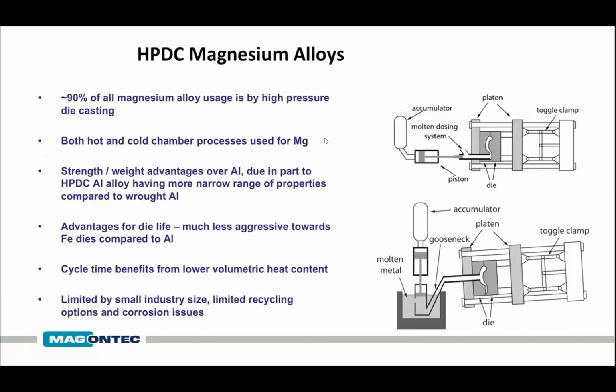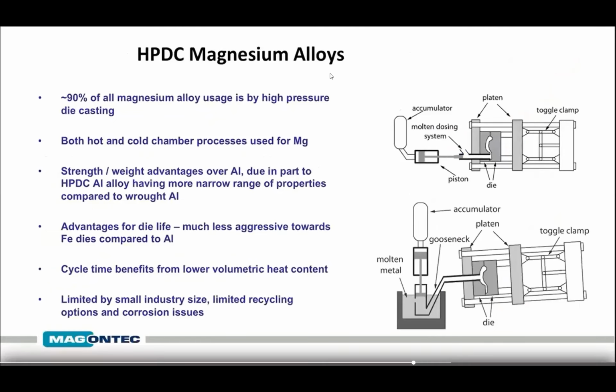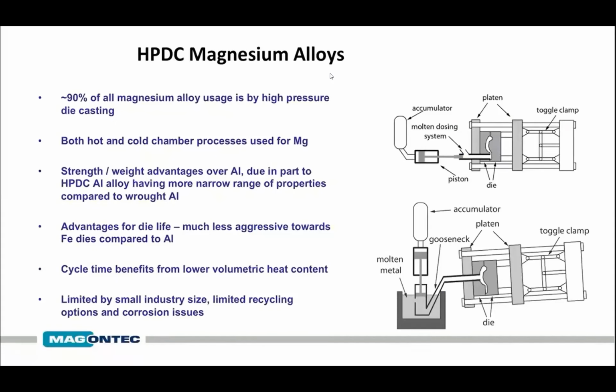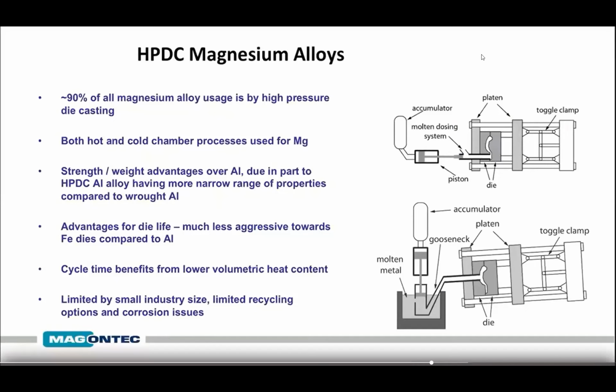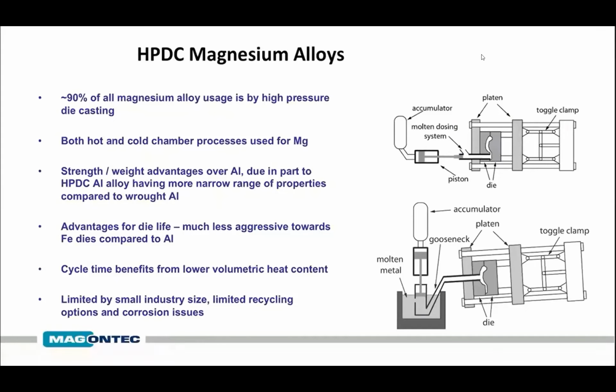So the overwhelming majority of magnesium alloy applications is high pressure die casting, something like 90%. Both common die casting processes, the hot chamber and cold chamber processes, are suitable for magnesium. In comparison, aluminium is really only used for the cold chamber process, and the other main metal used for hot chamber is zinc. So magnesium has a significant advantage in being able to be used for the hot chamber process, which has production efficiencies and good yields.